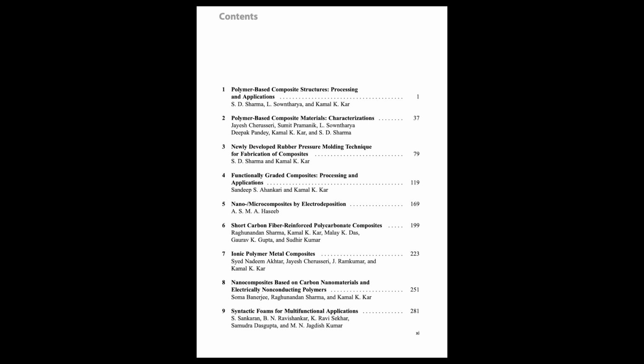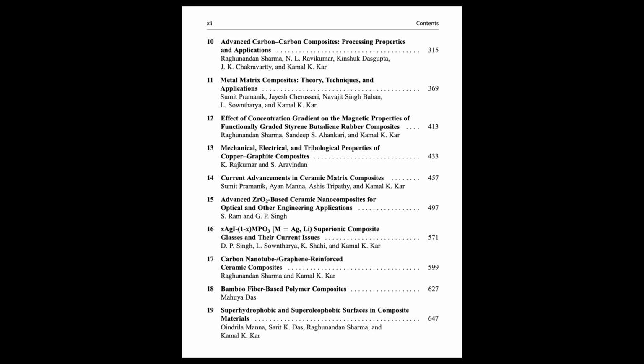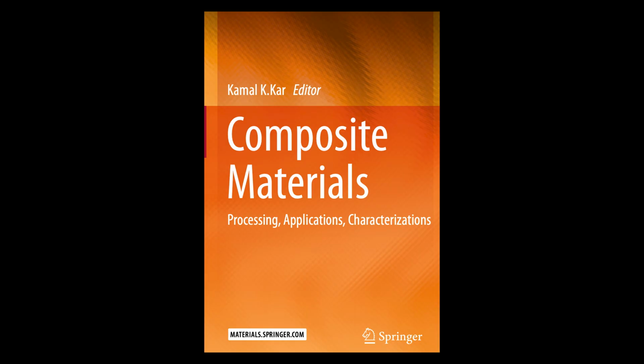We saw examples in polymers, too. Yeah, graded cross-link density in rubber, changing stiffness in polyurethane nanocomposites, shifts in the glass transition temperature in rubber, and a big one, biological prostheses. Why FGMs for implants? Better matching the properties of natural bone and tissue, minimizing material mismatch. You can even grade porosity to encourage bone ingrowth, like with those nanohydroxyapatite PVA biocomposites.